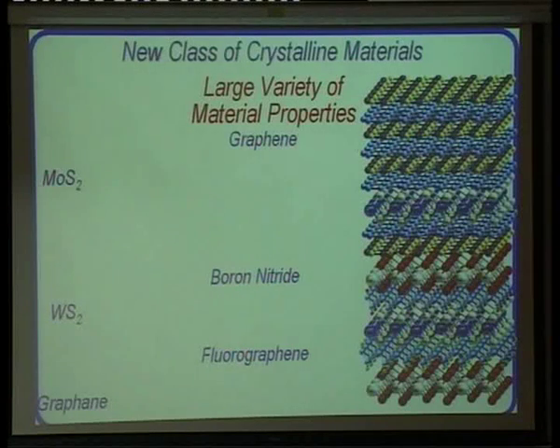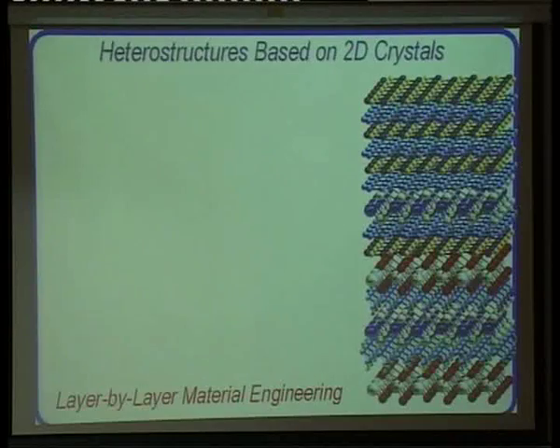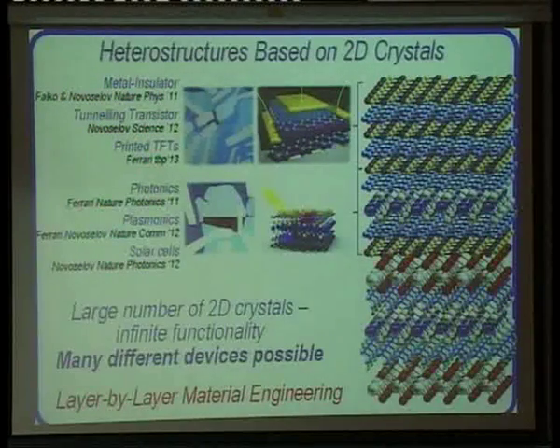But of course, as I said before, there are already people looking at how to grow graphene on BN, how to do multilayers by CVD, and by solution processing. So it will take time, but in terms of physics, you can think of all sorts of things you can do by putting together these materials artificially. As I said, there are already some initial results published, mostly in 11, 12, 13, so very recently, on these new materials. And in fact, in principle, we have layer-by-layer material engineering with almost infinite possibilities. The limit is how either lucky or clever you are in finding out which is the combination that gives you a good result or something exciting.